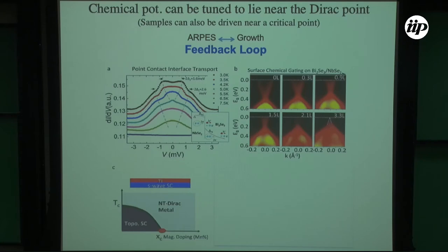Can we make a critical topological Dirac superconductor? Using the materials algorithm I showed, in addition to what I was doing, we can also do surface gating, chemical gating on the surface by dopant molecules. You can see that without any surface dopant, your Fermi level is up here, but you want to be at the Dirac nodal point. With chemical doping, we developed an algorithm so that you can actually place your chemical potential there. So this is where we stand at this point. In other words, this state is a quantum critical topological superconductor, if you like, by construction.